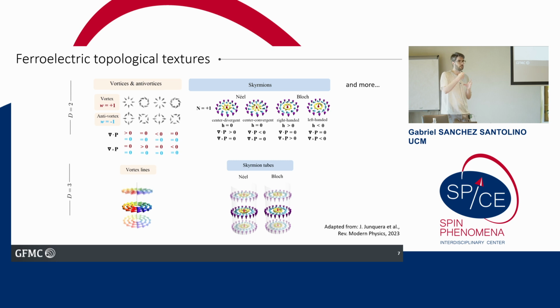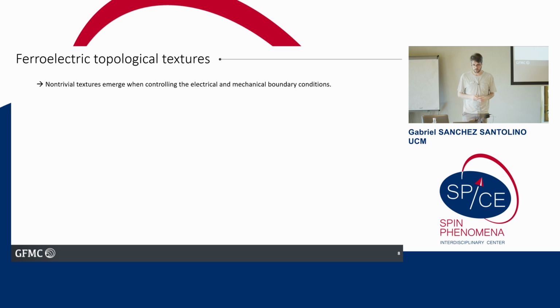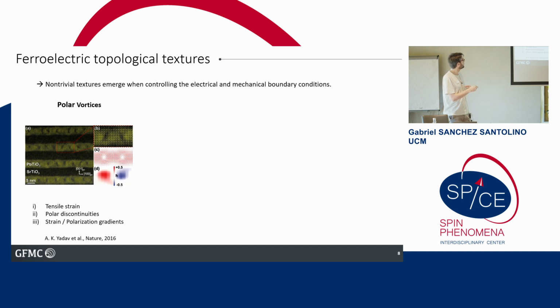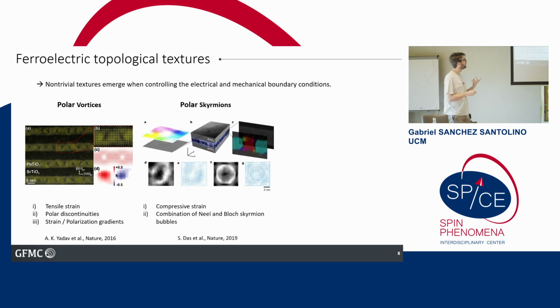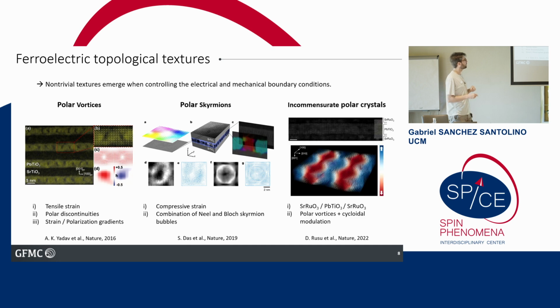So this continuous rotation of the polarization comes with a very high energy cost. In order to stabilize these kinds of structures, people started making superlattices, like Fernando showed yesterday. They started mixing paraelectrics with ferroelectrics, with different layer thicknesses, with different materials grown on different substrates. So you will have tensile strain or compressive strain from the substrate, and people were able to stabilize these ferroelectric vortices, also ferroelectric bubbles.